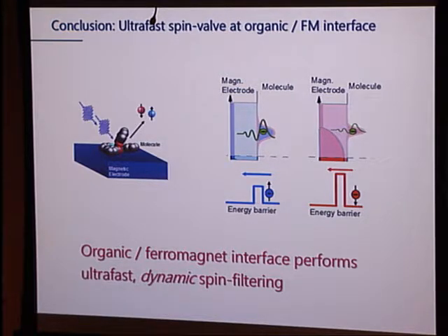Now, I'll say here that the dirty little secret is you have to really be careful not to get any oxide on the cobalt because that will scramble the spin direction. And so we pay a lot of attention to making sure that we're not forming oxides as best as we can. We prepare these surfaces fresh every time by evaporating cobalt over and over again and make sure that the chamber is clean. But they're in-plane magnetized? Yeah, not perpendicular magnetized. That's HCP cobalt, right? This is HCP cobalt, yeah. It's grown on copper 111, so that'll make it HCP.